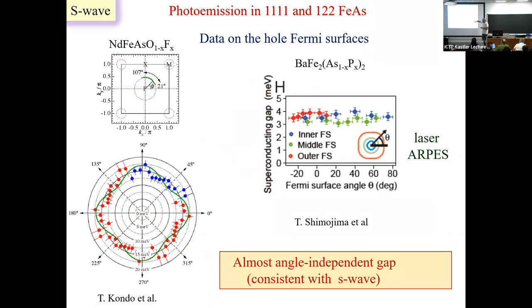Okay, so now a piece of evidence. One is simple. How to prove that the system is s-wave, not d-wave? Well, do ARPES and look at the Fermi surface. This is the original ARPES from the Iowa group. This is the Kaminski group. This is laser ARPES from Shin, who unfortunately also passed away recently. Clearly it shows this is really very accurate ARPES data, which includes also another Fermi surface that I didn't talk about. And it shows that the gap doesn't change as you make a circle around the Fermi surface. This is s-wave. I cannot imagine that this is not s-wave from this data.